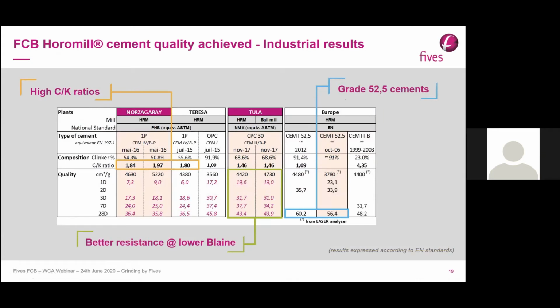To have some more example of cement quality, we can here have recent industrial results. In the middle, the plant of Tula is an existing grinding plant in Mexico, having both technologies, Horomill from FCB with aerodecanter and ball mill from FCB with a TSV classifier. So we had the opportunity to compare the two technologies for the same cement. And we confirm here, as you can see on these figures, that we obtain the same quality of cement, for sure with a significant saving in energy, with a lower Blaine, exactly 300 Blaine lower, just to confirm what has been said before with another reference.